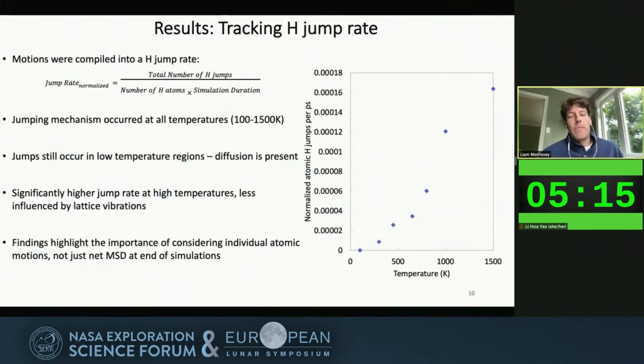After showing that motion, we then wanted to find a way to better track diffusion beyond just the MSD. So we took these motions and compiled them into what we call a normalized jump rate, where we take the total number of H jumps and divide it by the number of atoms multiplied by the duration of the simulation. You can see those findings in the figure on the right.